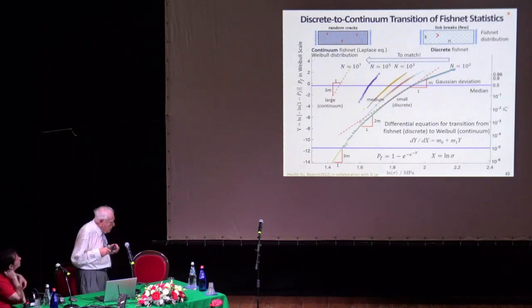Now, we are trying to extend this. These calculations were for fishnets of several hundred links. Now, what happens if you have not 1,000 links, but 1 million of them, or 100,000? Then, obviously, it must go to a continuum. And you have a certain number of links, failure not with two links, but maybe with 20 links. They would form a crack in this continuum. What is interesting probabilistically, this continuum is a Laplace equation. And crack, you can show it's a Laplace equation, but crack can be solved. It's a positive geometry. So one crack would cause failure. So that must go to Weibull distribution.